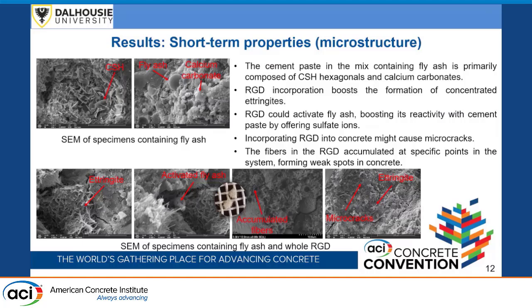We can also see some reactions on the fly ash particles that attach to the fly ash particles, and that shows the RGD can promote the reactivity of the fly ash, because in the specimen without recycled gypsum drywall, we don't have those reactions. For incorporation, we also see some micro cracks in the SEM image. We don't know exactly whether they are because of testing specimens after the compressive strength or they are originally there. So we are going to find it out.